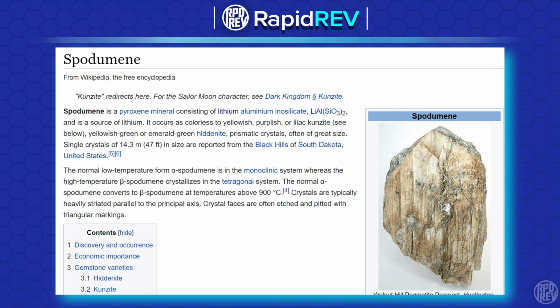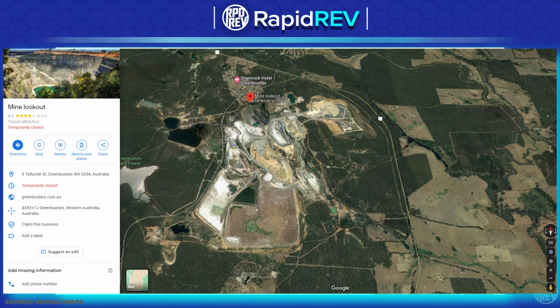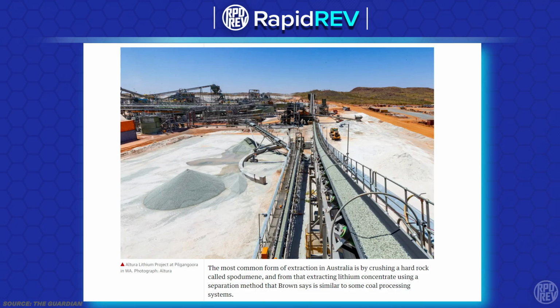Now, I mentioned two methods of lithium mining dominate, and the second is mining spodumene, a hard rock rich in lithium. Currently, mines in Australia lead the way in worldwide lithium production with Talison Lithium's Greenbushes mine. Located in a fairly flat region of Australia near the southwest coast, the Greenbushes mine has a hard rock rich in about 50% spodumene, with about 3.9% lithium oxide. However, the lithium in this hard rock is a little harder to extract, and the operating costs for this method are about twice that of brine extraction.